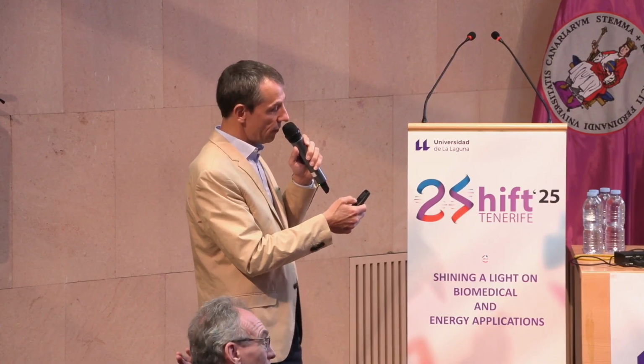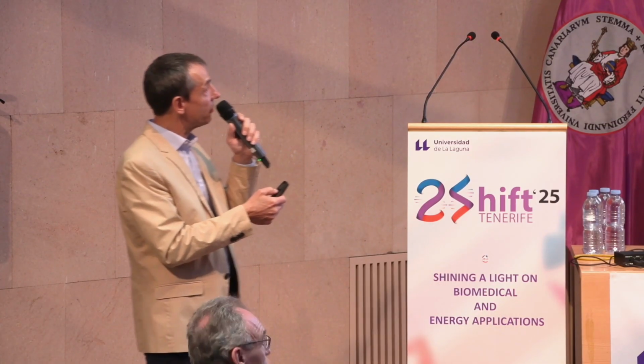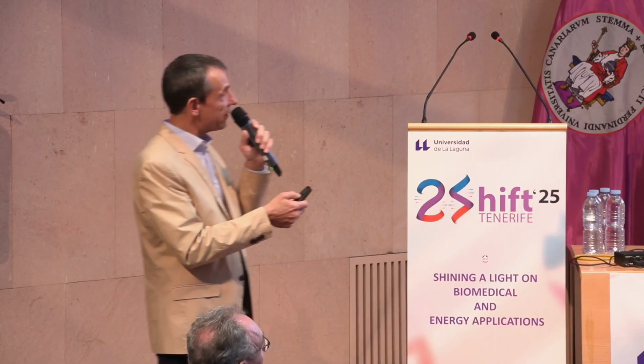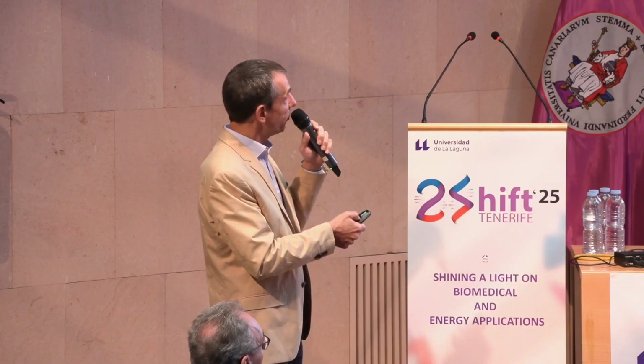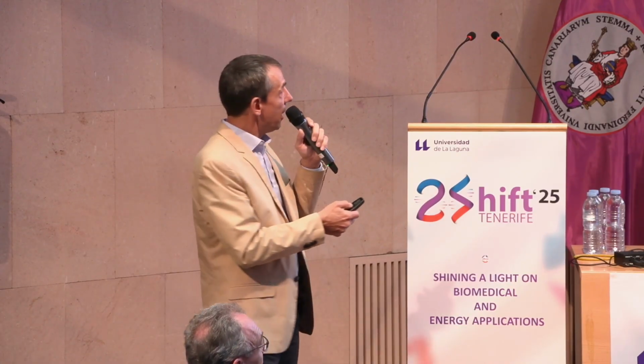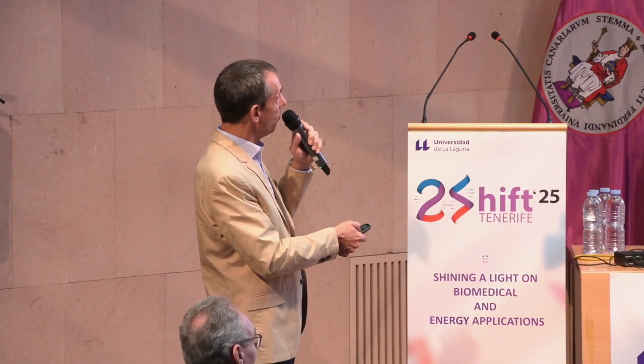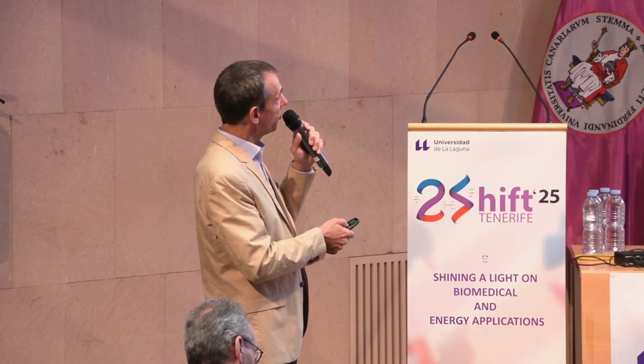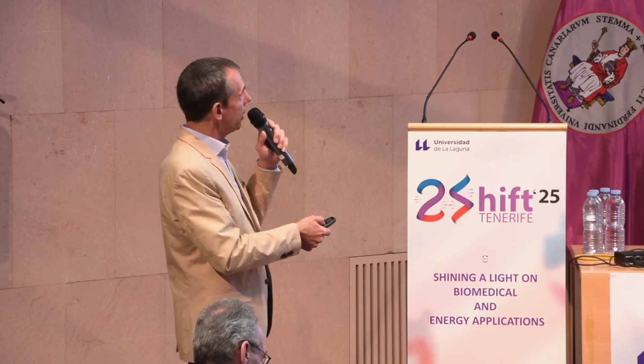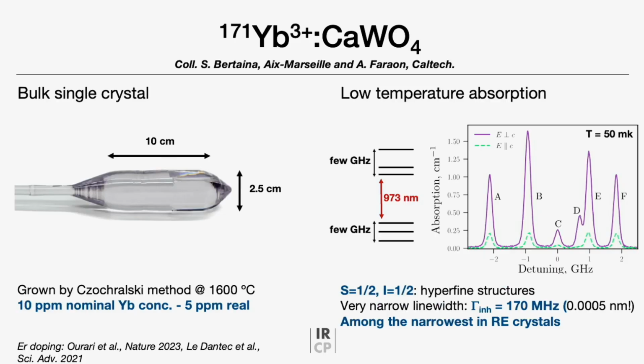These materials are grown as bulk single crystals by the Czochralski method. So we are pulling the crystal from the melt. Melting temperature is relatively low, 1,600 degrees C. And you see a boule here we obtained in the laboratory. As you can see, it's a crystal you can obtain with a very high quality, no bubbles, no fractures. It's really a very nice material.